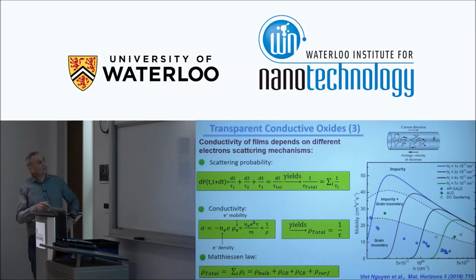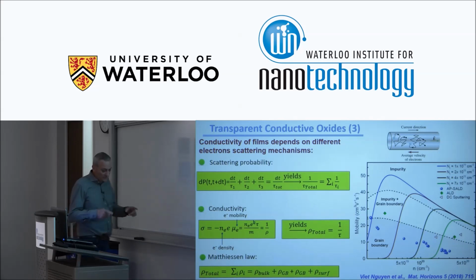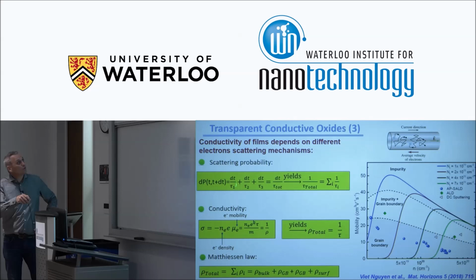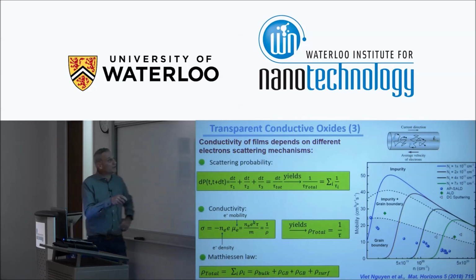So for sure, there are different electron scattering mechanisms. The probability for an electron of being scattered between the time t and t plus dt is equal to dt divided by τ1 plus dt divided by τ2 and so on, where τ1, τ2 and so on are the scattering times associated to different scattering mechanisms. So we have to add the inverse of these characteristic times. It means that the inverse of the total scattering time is the sum of the inverse of the scattering time for each mechanism.